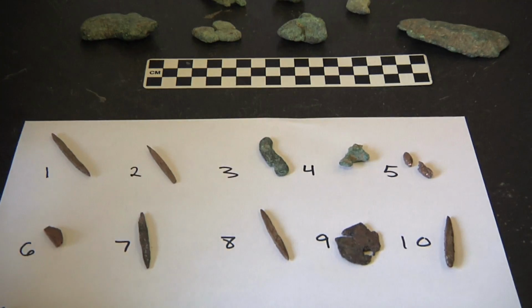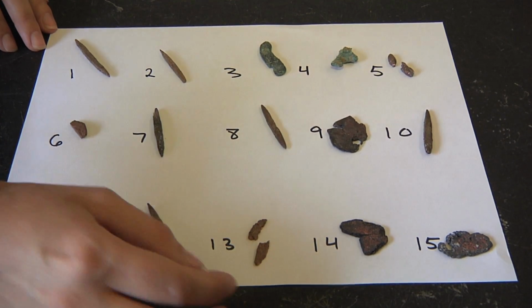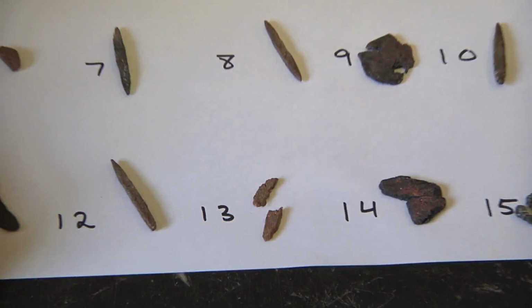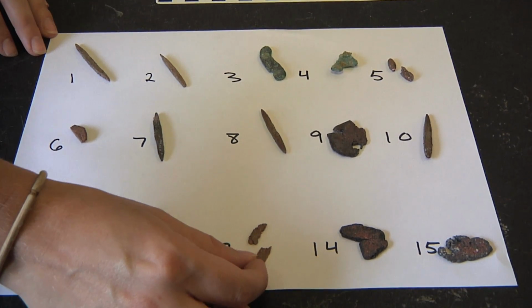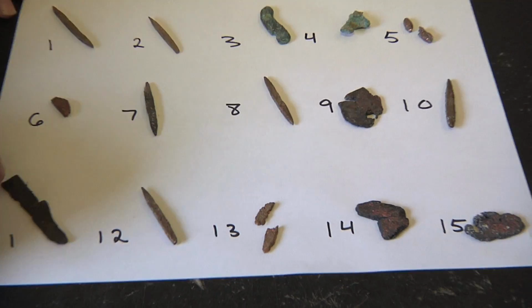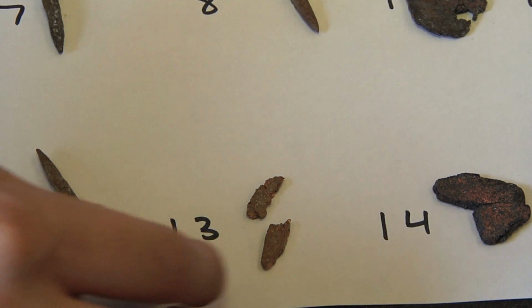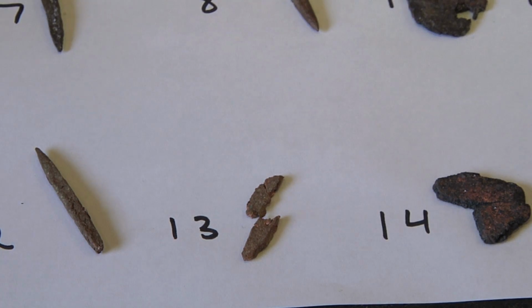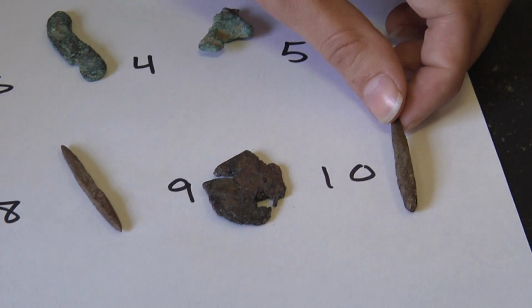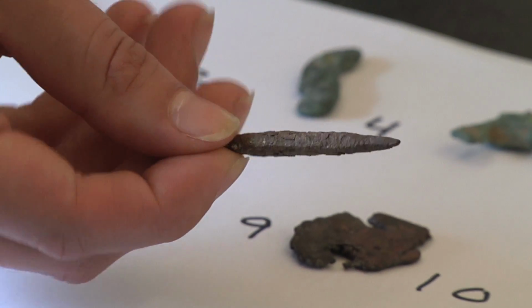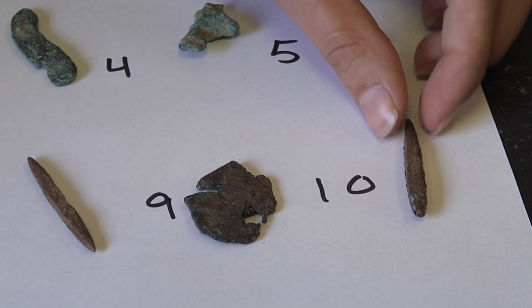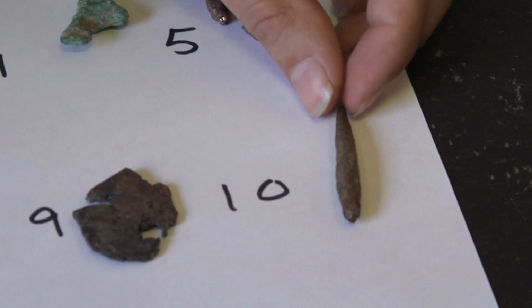Number 13 and 5 here are examples of failed attempts, basically because the nugget broke as we were shaping it. So what we may be looking at in some of these instances are material failures where the copper nugget was being worked by somebody, but it broke and wasn't able to be repaired or continued to be used as we were shaping it. With number 13, we don't have enough material to work with, so we just left it as is. Number 10 here is actually an example of a larger nugget that we were shaping into an awl, which broke into 3 pieces, and this piece was actually large enough to continue shaping.